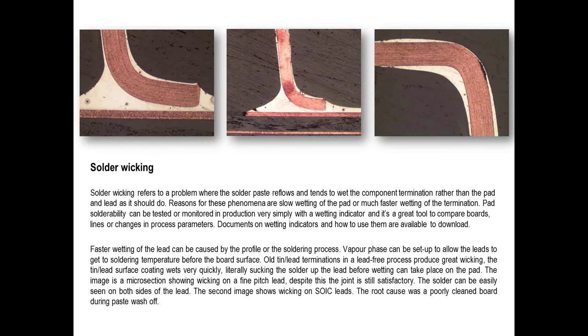But these examples here can show the effect of how solder can wick away from a surface because there's better wetting on one surface than another. So as an example, if you're running a tin lead or lead-free process through convection, but with nitrogen, you'll get better wetting. So let's say the pin solders quicker than the pad, then the solder is inevitably going to wick up the pin. So it's taking volume of solder away from the pad. If that happens really, really quickly because of your very, very pure environment, then again, you could have an open solder joint because of it.